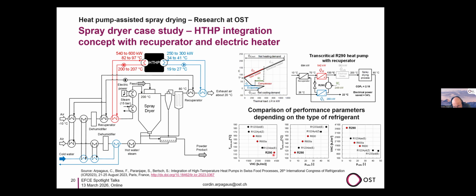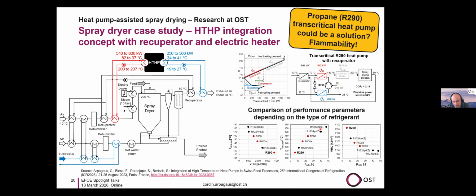So as you can see here for propane, this achieves a very high heating capacity, but the sink outlet temperature, so the achievable temperature is limited to probably 130 degrees. Like CO2 was also somehow limited to 120 degrees in the former case. With other gases, we could reach 160 degrees, for example, butane, to have that. And then this gives some compromise. Okay, so propane was found to be quite a suitable solution, but it is flammable. So would this be allowed in a spray dryer facility to have a flammable gas inside this spray dryer? That's a good question.